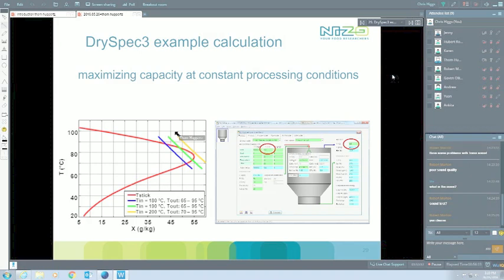And we can start looking further, trying different combinations, and rather than having to do these in the dryer, running a lot of trials and creating a lot of issues, we can do them on the computer. We can see a combination of 190 degrees inlet, outlet in the 65 to 95 area. We're actually nicely in that zone where we don't get a lot of stickiness, but we run at maximum capacity, and we can make the most of our dryer.